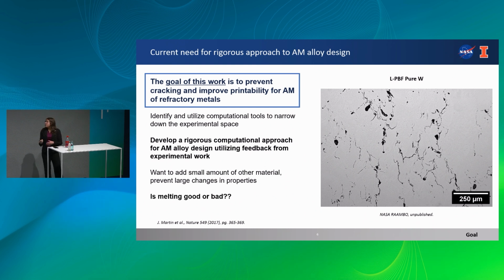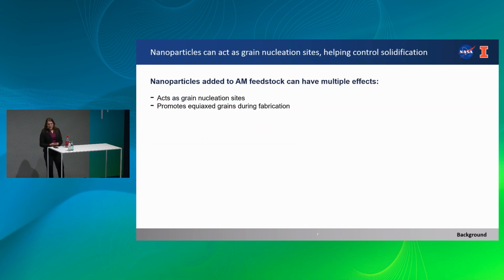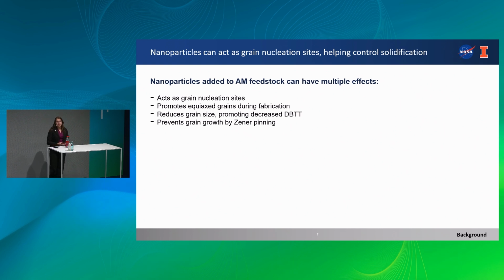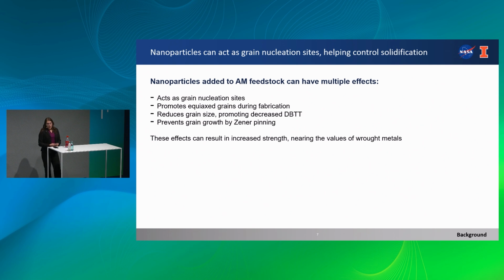And really, one big question we want to answer is: is melting good or bad? A lot of the research currently has shown a variety of effects of the nanoparticles. They can act as nucleation sites and help promote equiaxed grain formation during fabrication. Additionally, this helps reduce the grain size, promoting a decreased ductile to brittle transition temperature, reducing that brittleness, and they also act as Zener pinning sites to help reduce grain growth during heat treatment. And all these effects can really help increase the strength, nearing values that are close to wrought a lot of times.